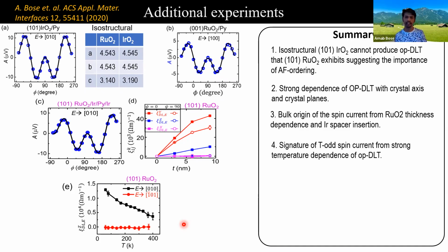This is, again, in contrast with the regular spin Hall effect. Because in that case, if the origin is the spin Berry curvature and within the intrinsic limit, we do not expect very strong temperature dependence, unlike this case. So all this together are in agreement with the theoretical predictions of the spin split bands of ruthenium dioxide that could lead to very extraordinary spin current.